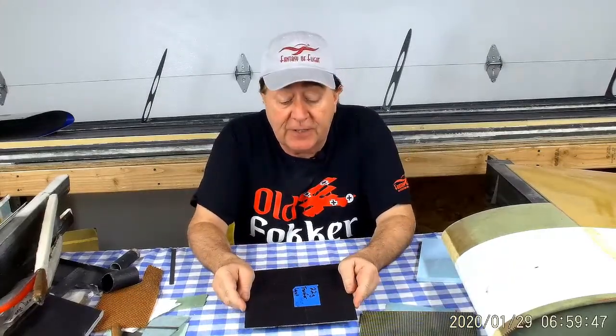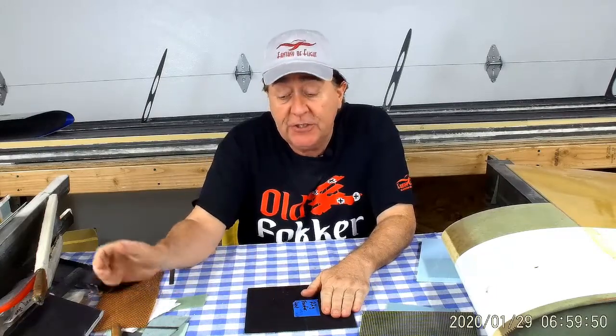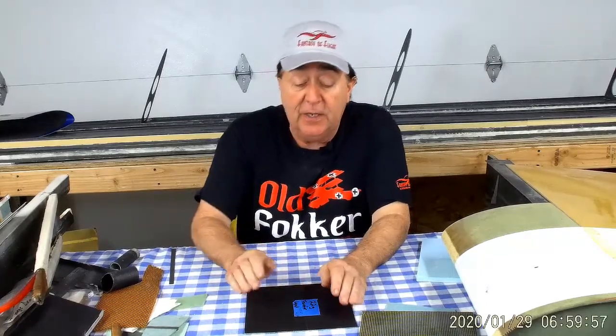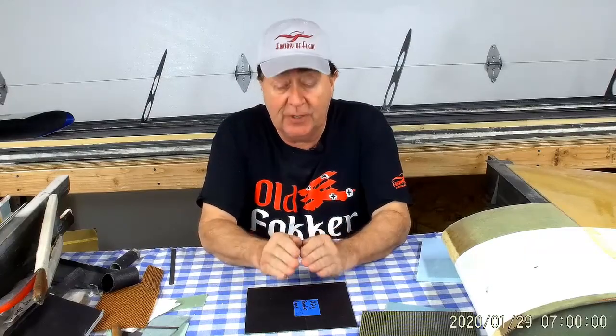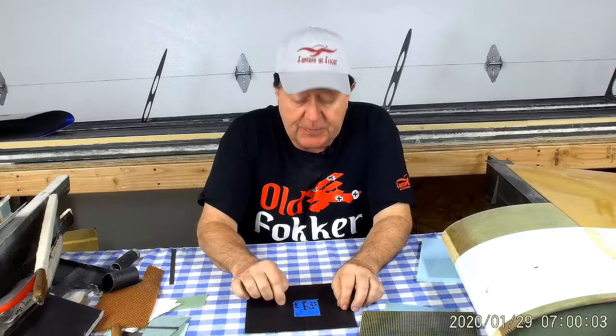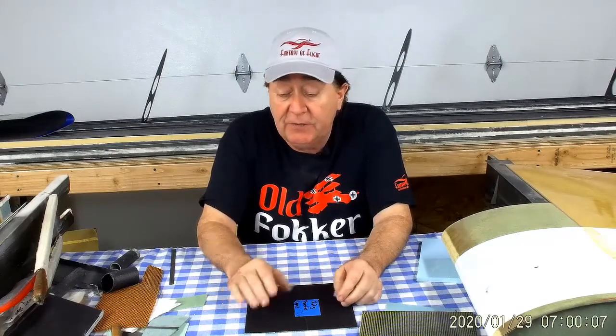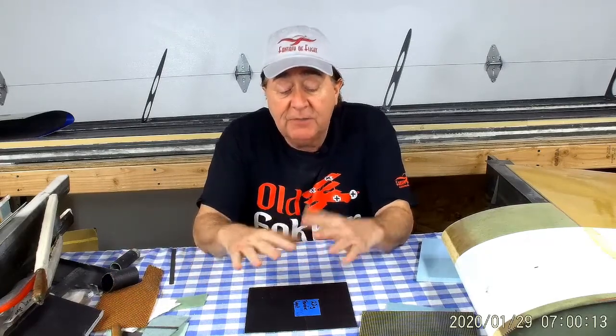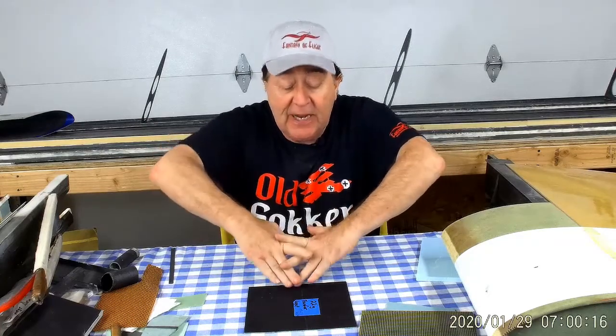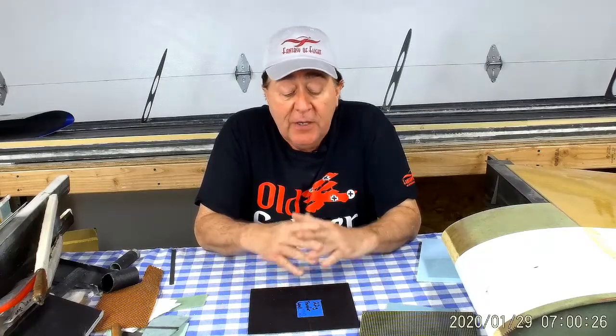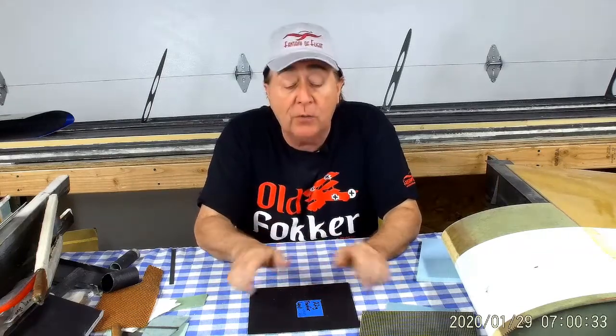This one is a transfer layup, where I take the fabric and put it on a plastic sheet and wet out the fabric completely and then transfer it to the foam and squeegee it onto the foam, in hopes that it doesn't transfer quite as much resin. What happens is there's always little spaces in the fabric, little openings between the weave, and when you wet it out on the plastic, that stays behind when you pick it up. You can imagine if it were a really loose weave like this, the epoxy that's sitting in the gap here, only some of it goes with the fabric and some of it stays behind stuck on the plastic. And that is generally extra resin that's not needed in order to do the layup. The only resin that's needed to do the layup is what's actually wetting out the fabric, the tows that are woven together.